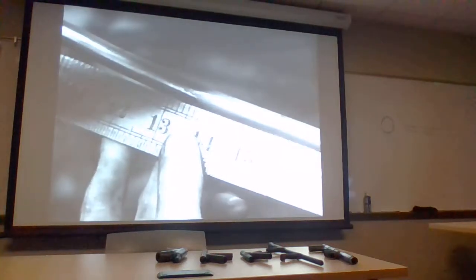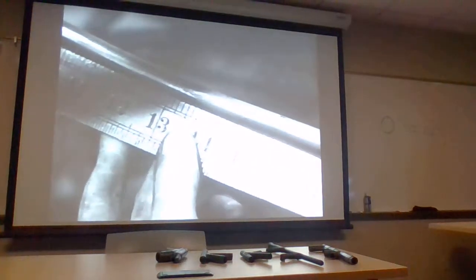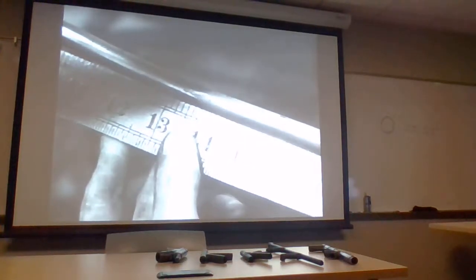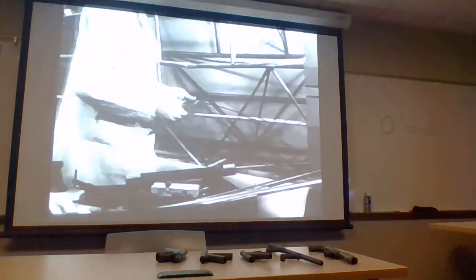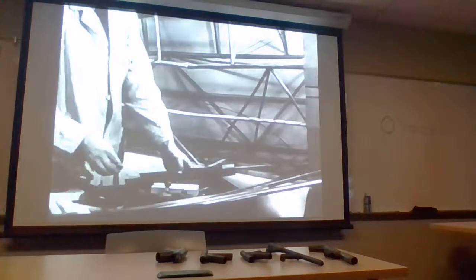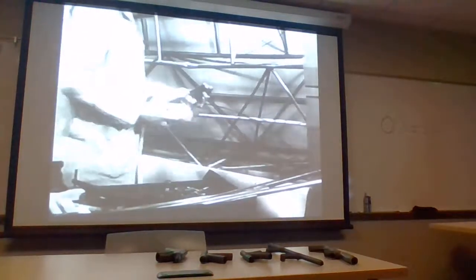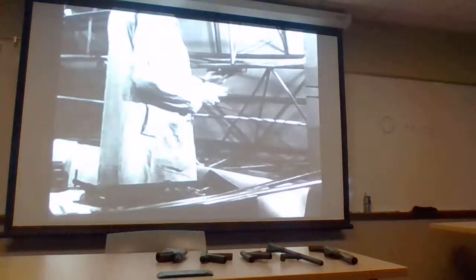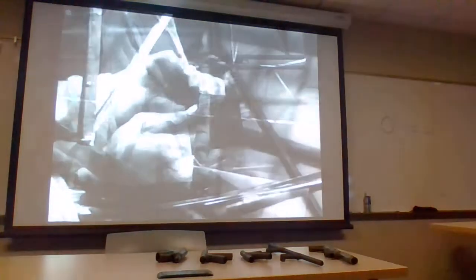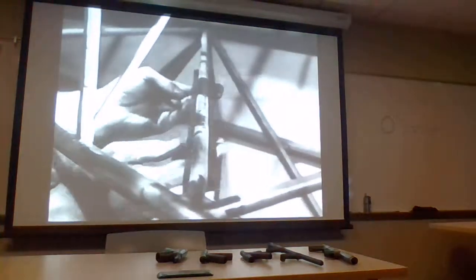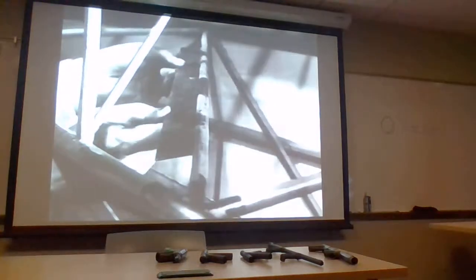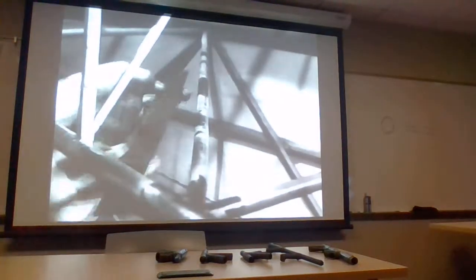Check the tube with a straight edge. Too much allowance was made for spring back, and the tube is now bent beyond the straight position. It must be bent back a little. Apply pressure in the opposite direction and continue to straighten the tube until your checks with the straight edge indicate the tube is perfectly straight.